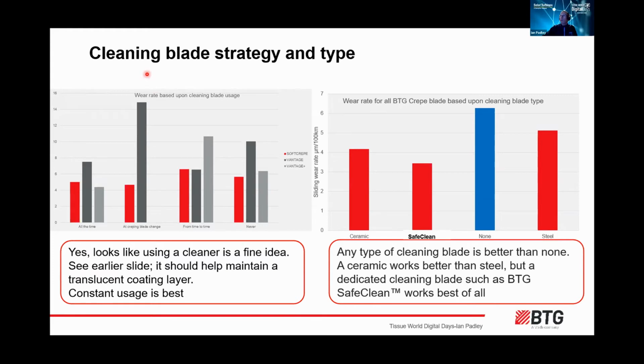But another thing we would employ as a strategy on a Yankee is the cleaning blade. Let's look at an analysis of cleaning blade wear data. Again, lower is better. Using a cleaning blade all the time appears to be a pretty good idea. All other things being equal, we're getting lower wear. Only using a cleaning blade at blade change, certainly for one of the blade types, a very common one, gives quite high wear. Same from time to time, with intermittent cleaning blade usage or never using a cleaning blade at all, we see that the wear on the creping blade is generally higher. So it should be fairly common sense. If we're using a cleaning blade, we should be maintaining a nice translucent, even coating layer, and that's going to be reflected in good wear on the creping blade.